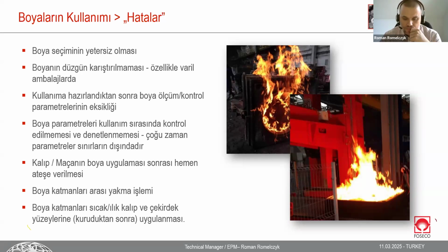What's more, I will touch on this point later, very often the coating is also not controlled during the preparation and after the application. So viscosity, density, Baumé, wet layer thickness, dry layer thickness, because wet layer thickness and dry layer thickness will always be different, because of shrinking during the drying. If the carrier disappears, of course it's obvious that the coating will shrink a bit.